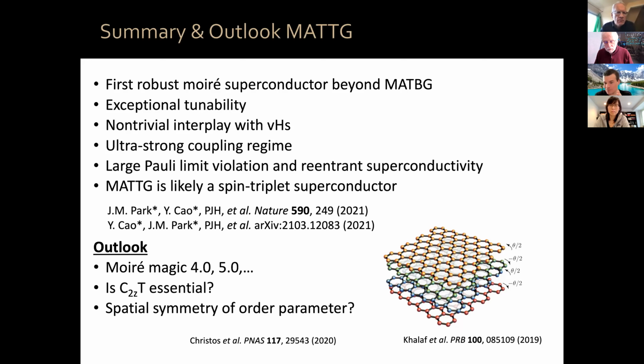So now, with the discovery of magic angle twisted trilayer graphene, the Viswanath group has come back and said, you see, all those other systems don't have C2zT symmetry. They are not robust superconductors. The only two so far discovered which are robust superconductors have C2zT symmetry. We think maybe it is due to the mechanism that we're proposing. We have to do more experiments, measure other layers, etc., to check that indeed this is the case.